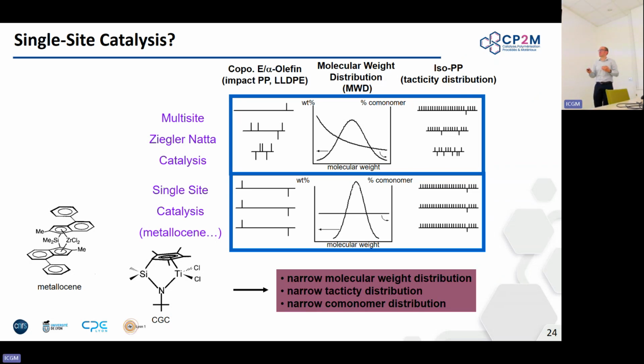But it has some advantages nonetheless, because Ziegler Natta catalysis, the conventional one, supported on magnesium dichloride, is very heterogeneous. Okay, it's multi-site catalysis. You generate a lot of different active sites on the surface, and you hope for the best. Maybe some of them will die, the ones that don't give you, for instance, a good stereoselectivity. And then on the long chain, you'll have a site that does its job really, really well and gives you perfectly isotactic PP. So you have heterogeneity even in the products. But because of what I said about the long chain being produced by a very regular site with perfect geometries and very active, then you don't care, because these will be just your process facilitators, the short chains, okay? And the long chains will give you the mechanical properties and the 165 melting point.